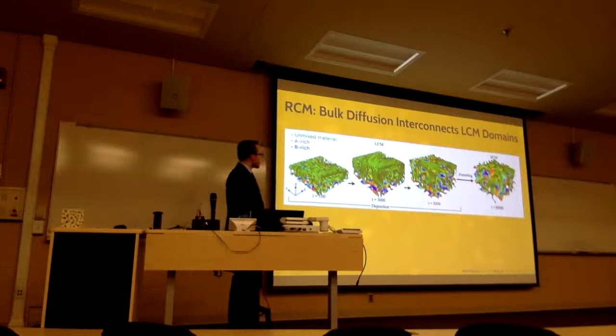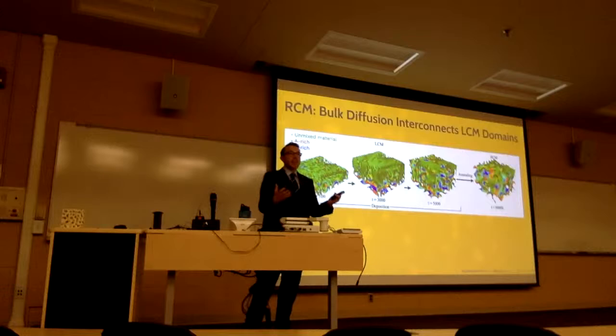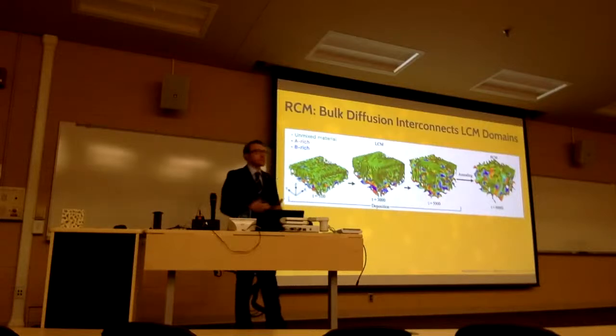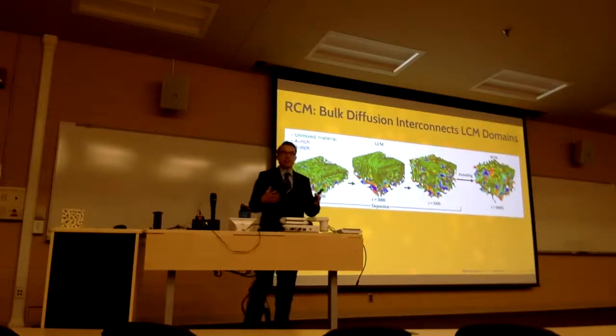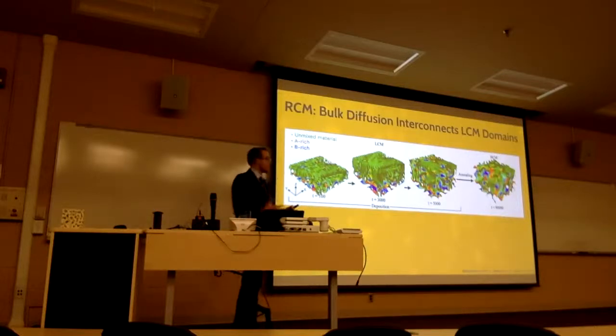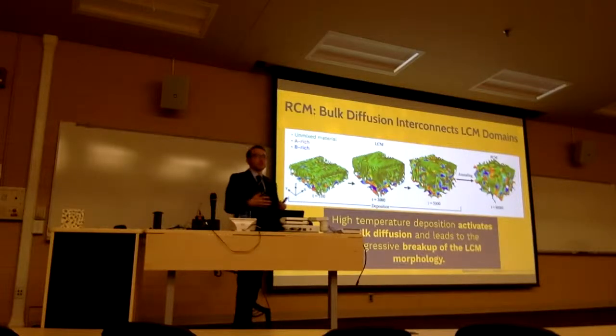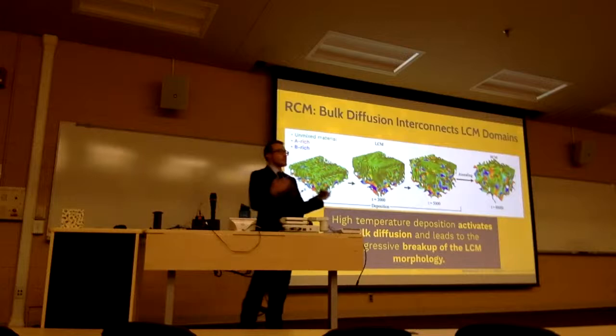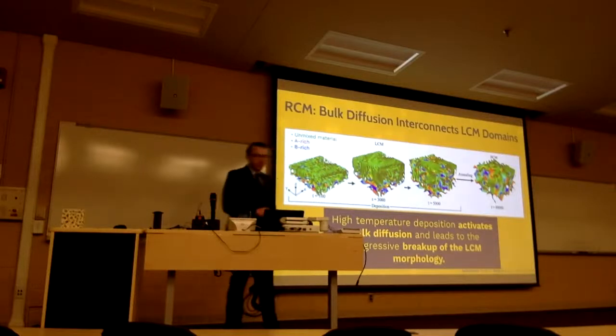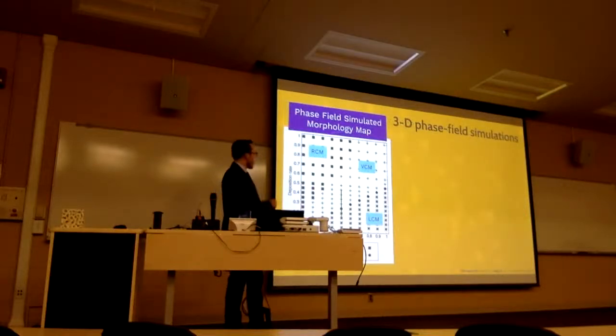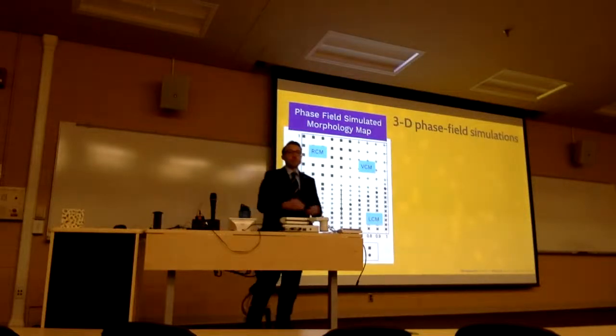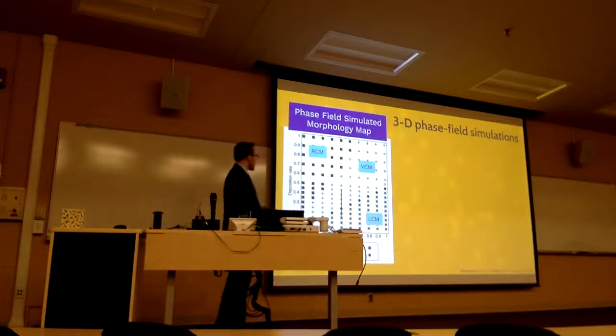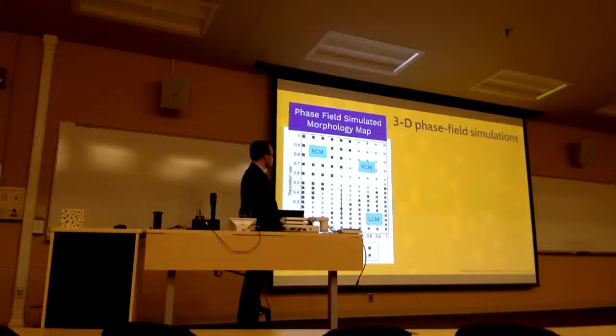So here's our results of our phase field simulation. And what you can see here is that the system tries at a high temperature to form this LCM-like morphology. But at this higher temperature, we've actually activated bulk diffusion. And that bulk diffusion leads to the breakup of the LCM-like morphology into a much more random interconnected structure like we saw in experiment. And so we were able to form a 3D morphology map, which you can see plotted here, which predicts the RCM-like morphology. You can see the regions of those morphologies labeled here.